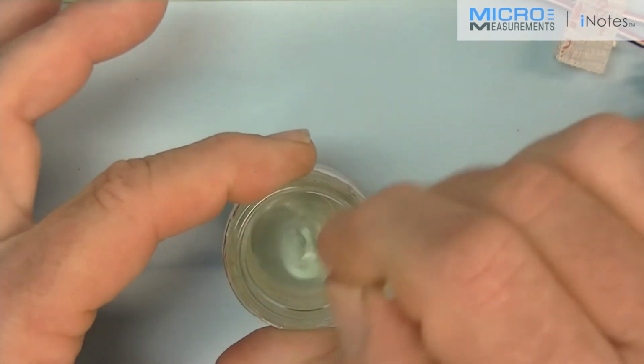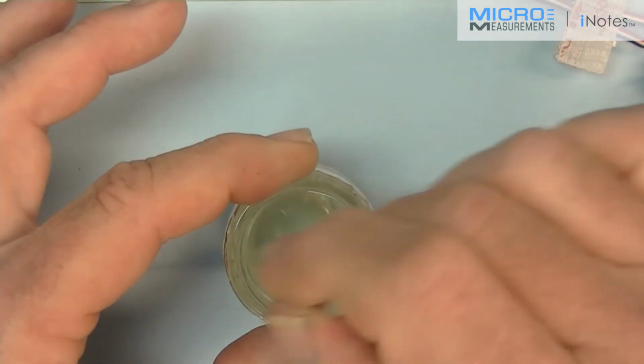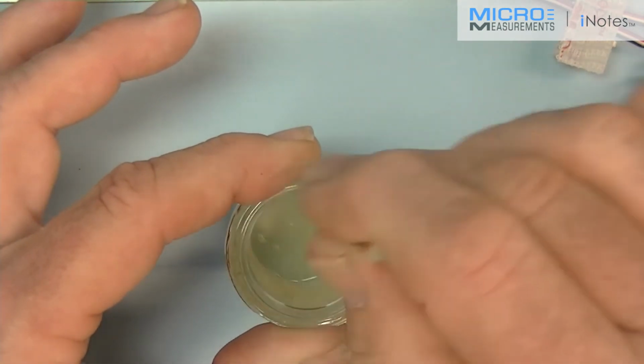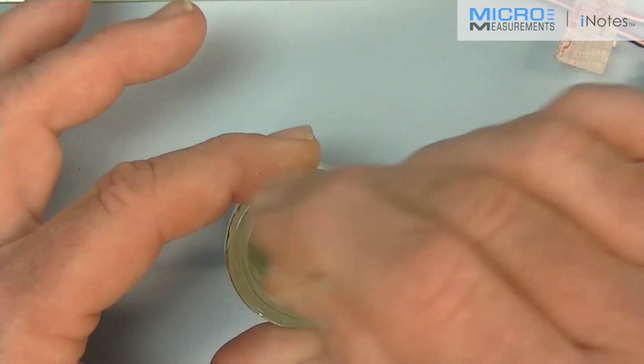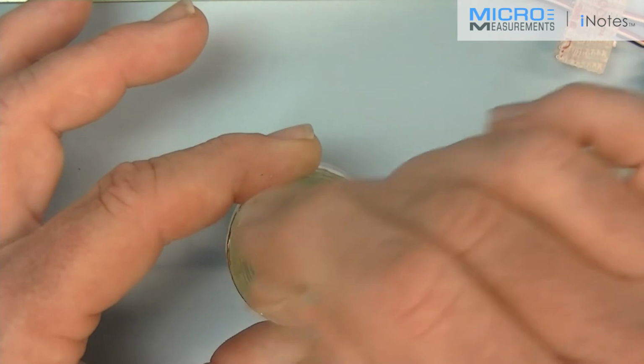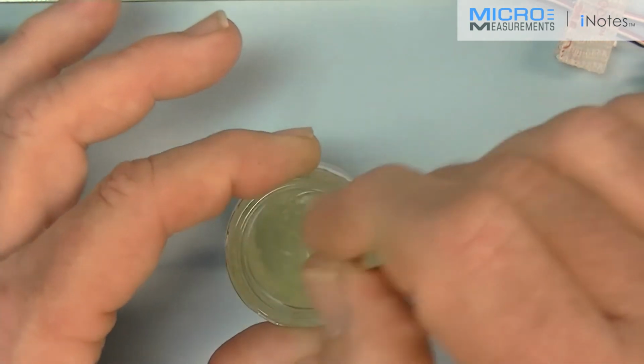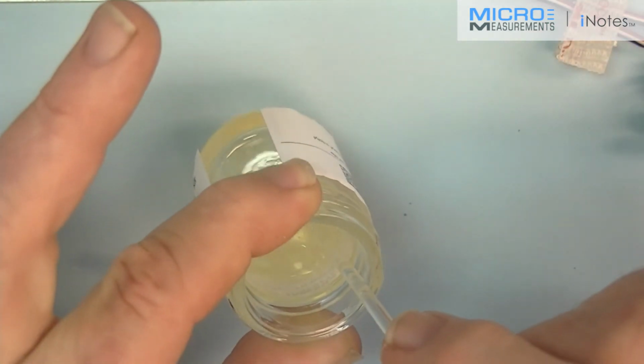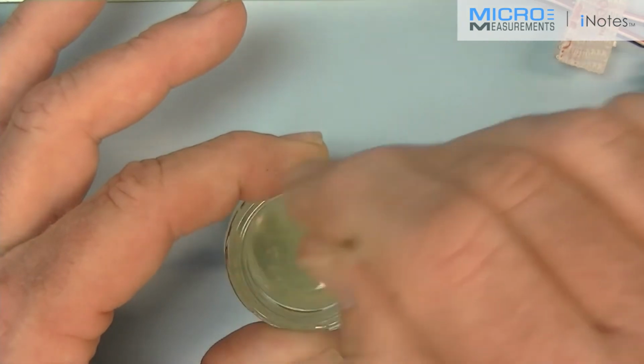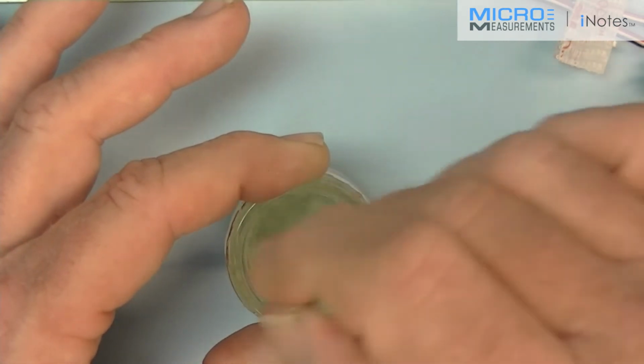I'm now going to begin the mixing process. I'm going to stir it for a full 5 minutes. This material is an exothermic reaction, and if you don't continue to stir it after you've started the mixing process, the center of it will get so hot as to kick over the adhesive prematurely. So I'm now going to stir. Note, I am holding the jar by the top of the rim of the jar, so I'm not introducing any more heat than is necessary. This material has a 15 to 20 minute pot life, and we don't want to shorten that even further.